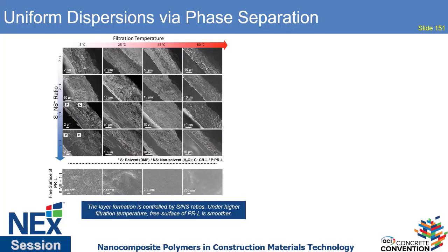And you can see at the very top, this looks like a composite that I showed first where everything looks fairly uniform. And as we go down, you can see there we have this very nice clean bilayer, and that depends on the solvent-non-solvent ratio as well as the temperature that we use when we introduce the polymer.